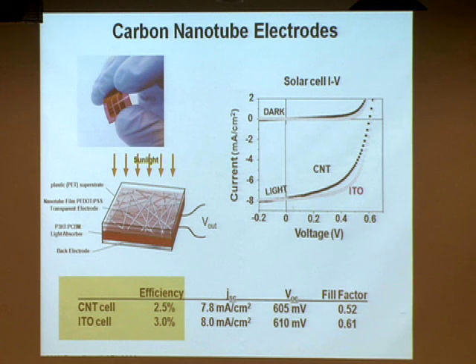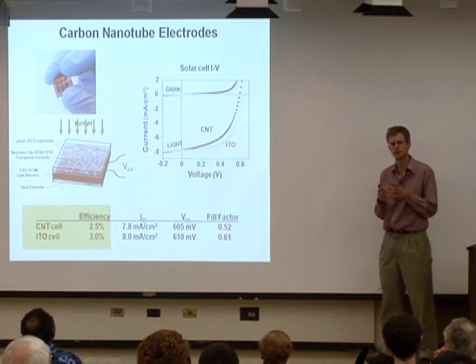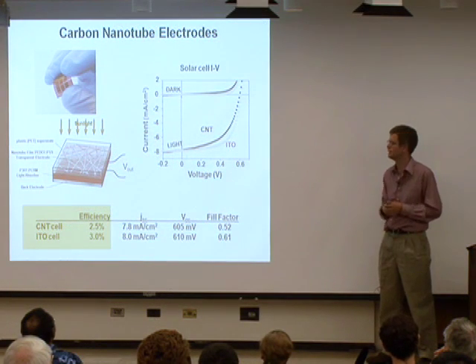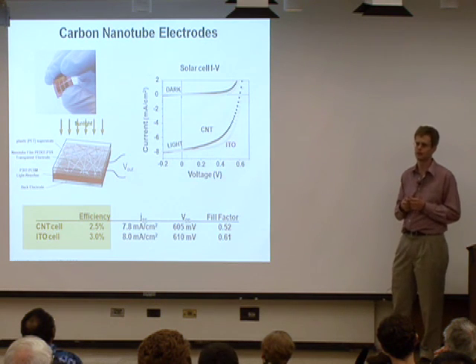Nanotubes conduct current, I think probably as well as any material that we know of. And so extremely small nanotubes, just 1 nanometer across, can carry a substantial amount of current. And consequently, we can have very, very light coverage with the nanotubes and get the conductivity that is needed. And because there's so few tubes, the absorption is relatively low.